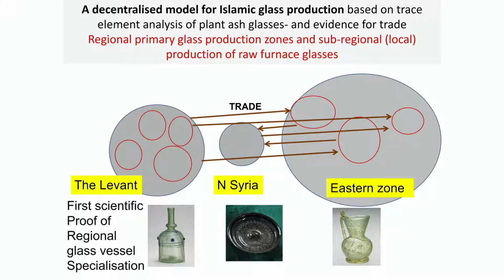And also the evidence for trade between these centers. Although, it has to be said, the majority of the data is associated with those centers. Sorry, I'll rephrase that. The majority of the results appear to be located for those particular centers. We find a degree of recycling for Samarra glass, but it looks as though they're recycling their own glass. So we have a mixing line for Samarra glass, but it looks like that basically they're retaining most of the glass within those centers where the glass is made, and only a small proportion is traded, which is handy if you're trying to provenance glass.